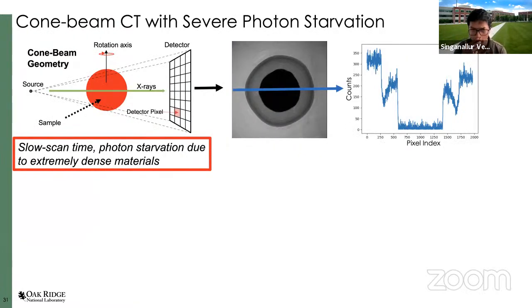So I'll conclude this part of the talk with a little example of yet another area we've been working on, which is cone beam CT. These are some nuclear fuel pellets, which are made of some uranium compound, and the outer cladding is made of much lighter elements. The goal for this task is to be able to characterize the degradation of these particles in order to build better nuclear reactors. These particles are foundational, but they're very hard to image using CT for this reason: the core is so dense that it attenuates the beam significantly.